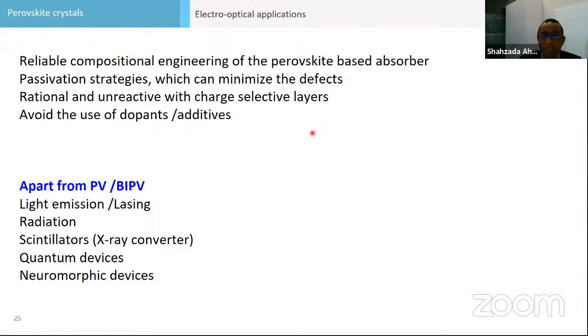Means p-type we call the hole and n-type the electron transport layer, or charge selective layer, because the perovskite is sandwiched between p-type and n-type semiconductors. We need to develop charge selective layers which are not reactive, more compatible and cost effective, and avoid the use of dopants and additives. Most of the time you can dope the perovskite or the charge selective layer to increase efficiency and performance, but the dopant diffuses with time, and you have a loss in efficiency, performance and reliability.